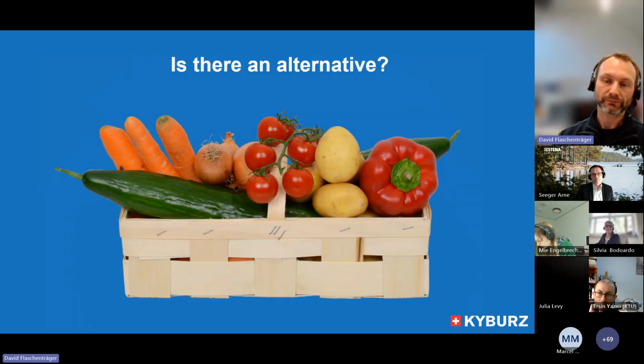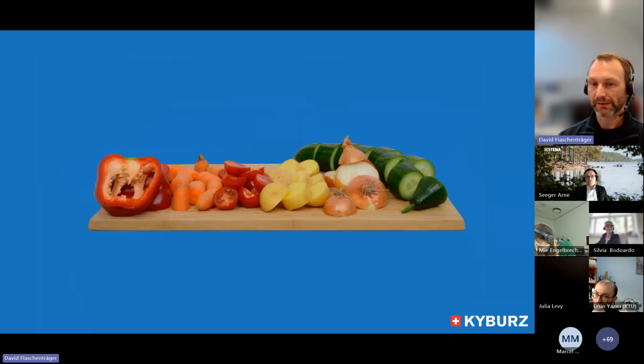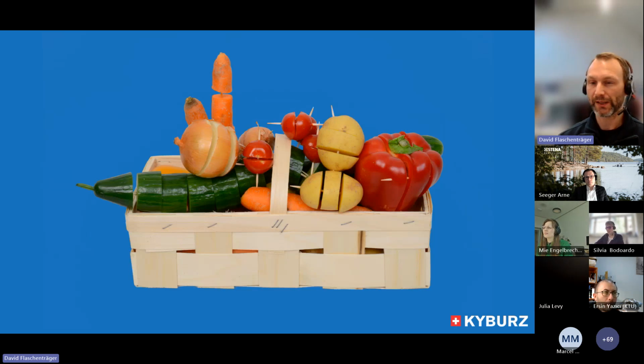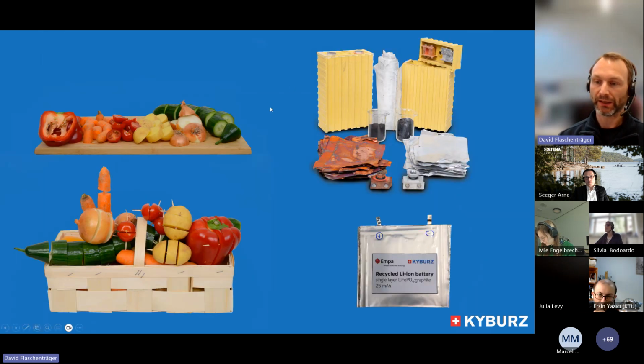So what do we do? We start again with a basket full of vegetables, and we cut them into slightly bigger pieces. And with, in that case, toothpicks and a little bit of fantasy, you can reassemble something that's eventually not exactly the same thing, but it's similar. And we could show that in the past. Back in 2022, we were able to show that from the materials we get out of our process, and that's what a battery cell looks like after going through our process, we can make a new battery. It's not high performance. It was not a developed product. It was just a proof of concept to showcase that in principle it's doable.